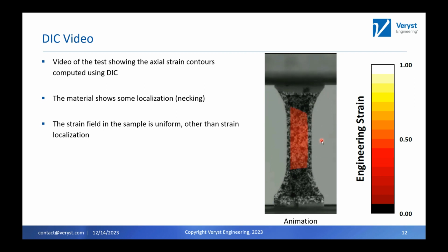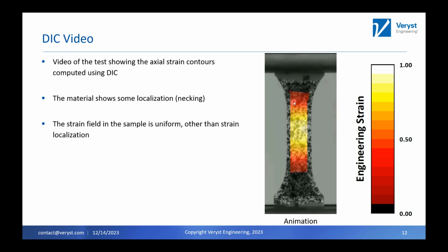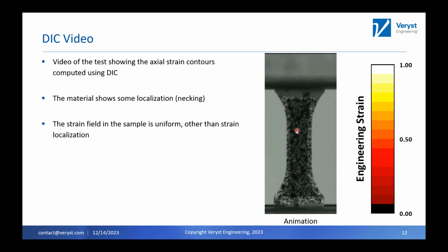So this can be really nice. This can be a good check to make sure you don't have any issues with the sample, or any alignment issues. You can see that we have a little bit of a non-uniform strain field as we start to load up here. You'll see that we got a little more strain on this side compared to the other. That's one of the things I like about DIC.